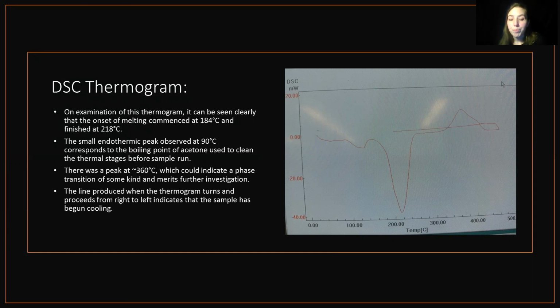were run. There was also a peak at approximately 360 degrees Celsius, which could indicate the presence of a phase transition. Further investigation is needed to confirm these findings. The line produced when the thermogram turns and proceeds from right to left indicates that the sample had begun to cool at that point.